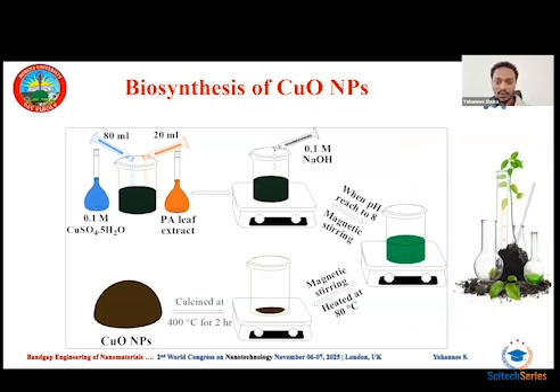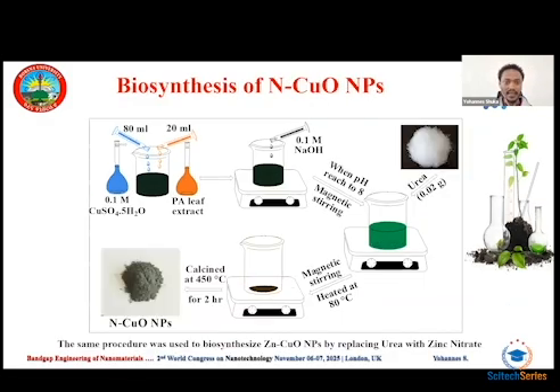The next one is biosynthesis of copper oxide nanoparticles. As you see in this slide, first 0.1 molar copper sulfate was used as the copper oxide precursor, and it was mixed with the leaf extract filtered in the previous experimental session. After mixing the two, the pH of the solution is adjusted to 8, and then the solution is stirred by using a magnetic stirrer at 80 degrees Celsius. The precipitate material is then transferred for calcination at 400 degrees Celsius. After 2 hours, we obtain the brown nano powder, which is copper oxide nanoparticles. The modification of the copper oxide semiconductor was conducted by adding urea, which is the source of nitrogen, at the stage of solution mixture.